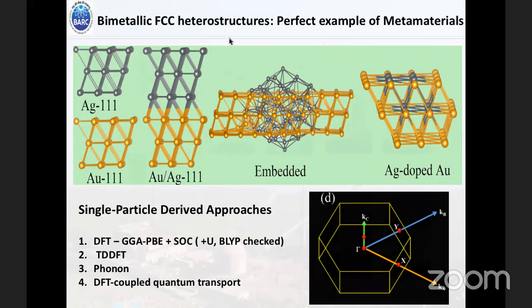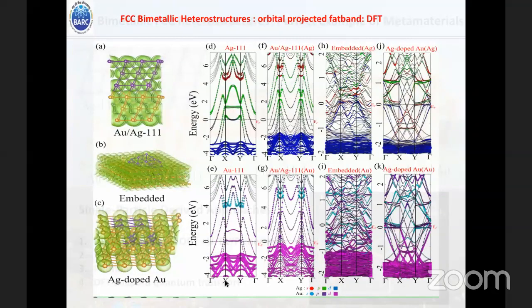And for FCC bimetallic heterostructure, if you just look at the orbital projected fat bands here, so these are Ag and Au111 systems, and you can see that near the Fermi level, for Ag it is p-d hybridized levels, and near Au it is s-d hybridized levels. And if you are making a large area interface between these two systems, then you can see that there is a large amount of charge transfer from Au111 to Ag111, so that there is an increase of curvature of the band structure near the Fermi level.